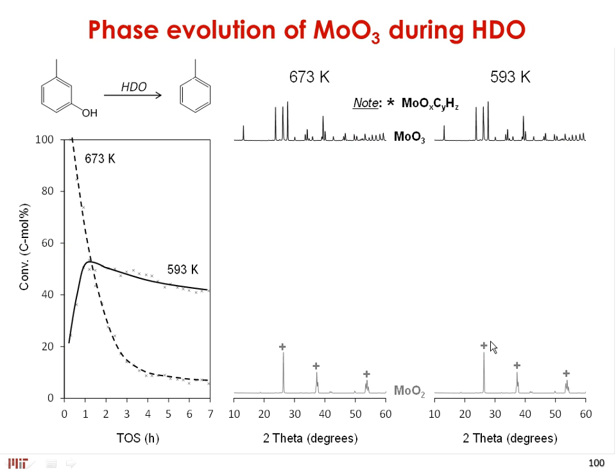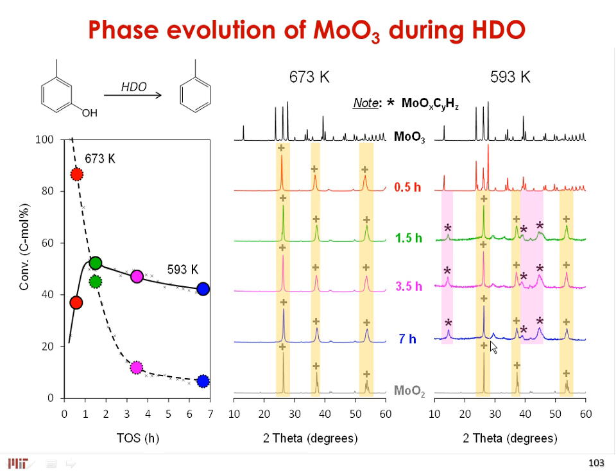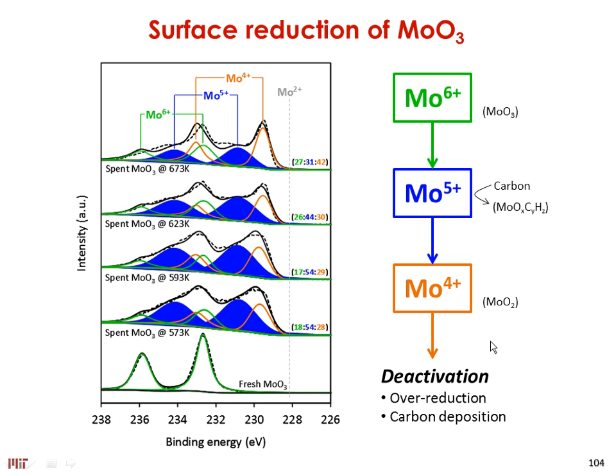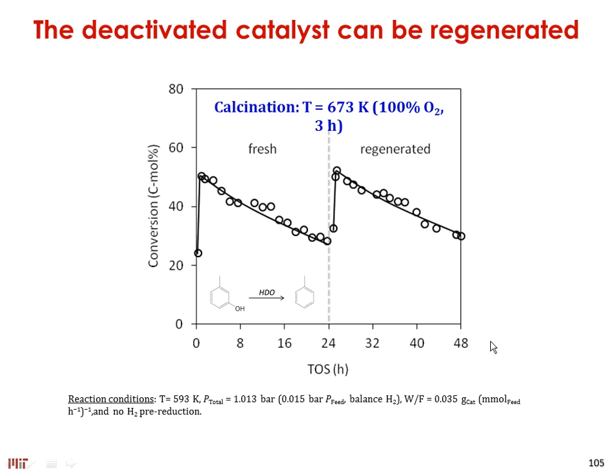And looking at in situ X-ray, we see a very interesting dynamic effect of the surface, where at 400 degrees C, we see a very quick transformation of our molybdenum trioxide into the dioxide. But when we go to a lower temperature, we see mostly a mixture of the MoO2 with this oxycarbohydrate. So this is where we're starting to look a little bit more carefully at what is going on. Looking at the XPS, we see a prevalence of this molybdenum +5 species, and we're trying to correlate the presence of this phase or this state with our reactivity. We know that after deactivation, we can again oxidize the material to MoO3, and then the entire cycle begins.